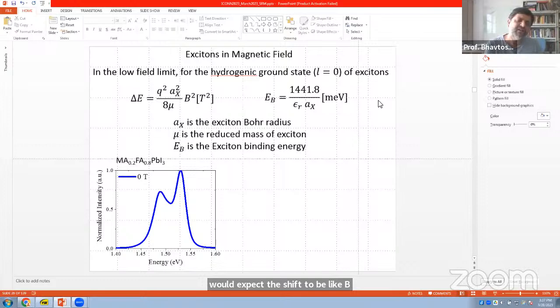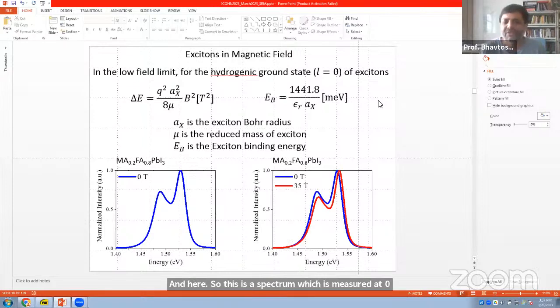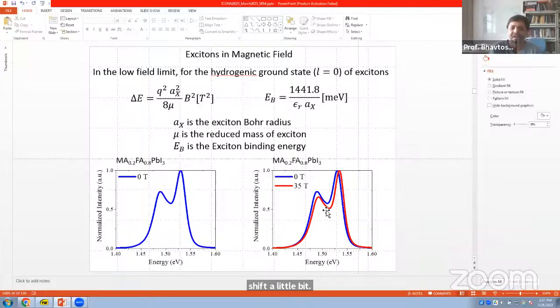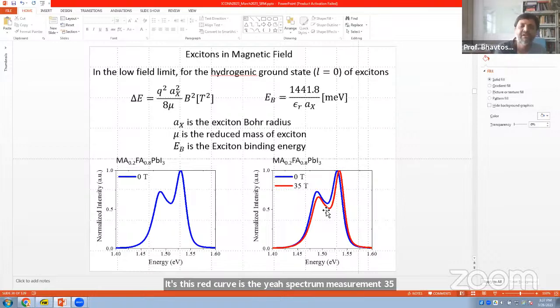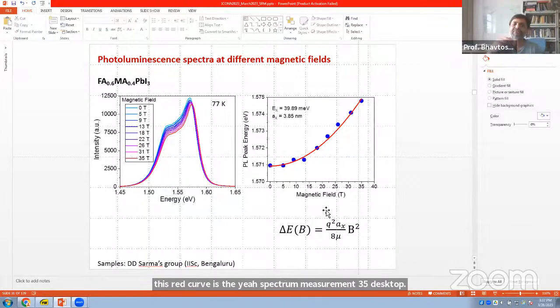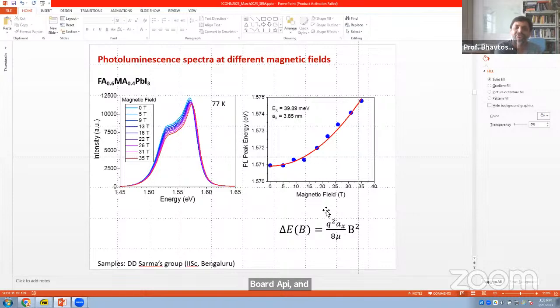And this is another spectrum taken from a hybrid halide perovskite sample, which is one of the materials I have been describing, whose parameters, for instance its Bohr radius, you would like to determine. This is a spectrum measured at zero Tesla. There are two peaks, and we see that each of these two peaks shifts a little bit. The red curve is the spectrum measured at 35 Tesla, and you see a slight shift in the peak. Using these kinds of shifts, we will try to determine the Bohr radii, the binding energy and the effective mass. So it should be B squared.